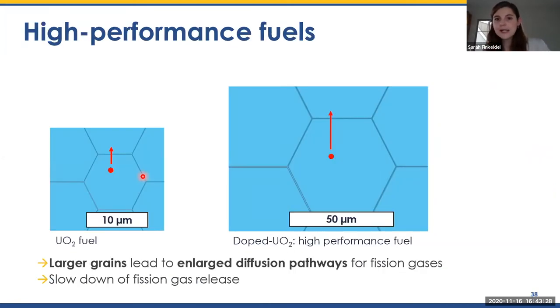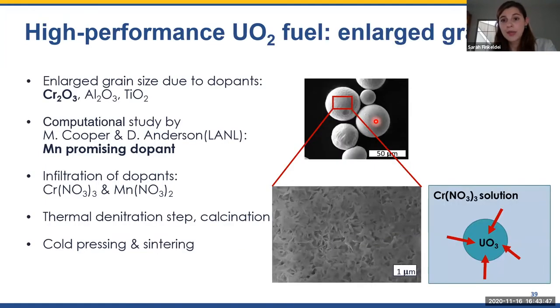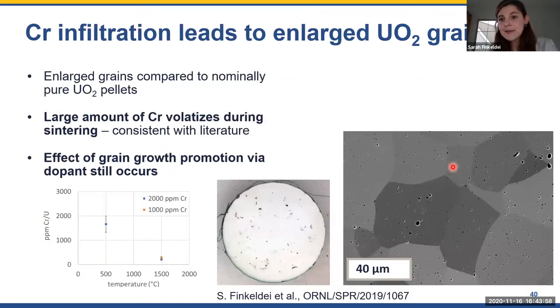For the other type of high-performance fuels, where we are trying to increase the grain size, the rationale behind it is that we elongate the diffusion pathway of fission gases to the grain boundaries, which have higher defect concentrations and therefore offer preferred escape routes for our fission gases. And how we are doing this is by infiltrating dopants like chromium, which is currently already applied in the ADOPT fuel from Westinghouse. And you can see that we obtain enlarged grains in the uranium dioxide, even though most of the chromium is volatilized during the sintering process. But this could also be beneficial since we then don't have to deal with any additional phase in our uranium dioxide fuel pellet anymore, but would still get the enlarged grain sizes.